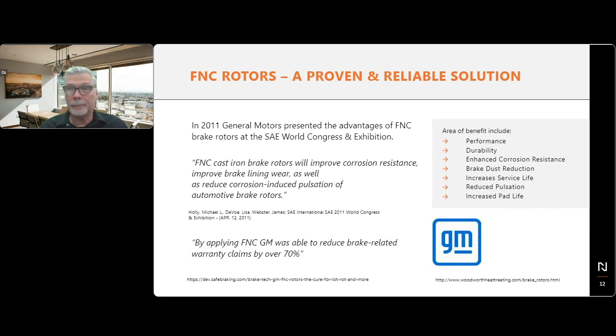Now, the idea of using FNC is absolutely not new, and it was introduced in North America for a very different purpose. The basic idea, and this was early 2010, I believe, was to basically increase service life, reduce brake pad wear, reduce warranty claims, among others. So the reduction of the brake pad wear and increase of service life points to a very important fact. FNC really modifies the structure of rotors and reduces abrasion of the braking pads, thus less particles.